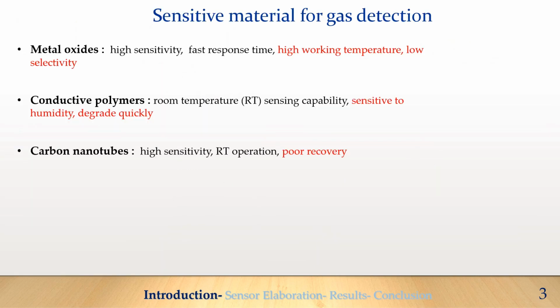During the last 3 decades, nanomaterials have been widely used in gas sensing devices. In particular, metal oxides are widely used because of their high sensitivity and fast response time. However, they usually work at high temperatures and they are not selective. Conducting polymer-based gas sensors can work at room temperature, but they are sensitive to humidity and degrade quickly. Carbon nanotubes are also used as sensitive materials for gas sensing because they can work at room temperature. However, they have poor recovery that limits their application.